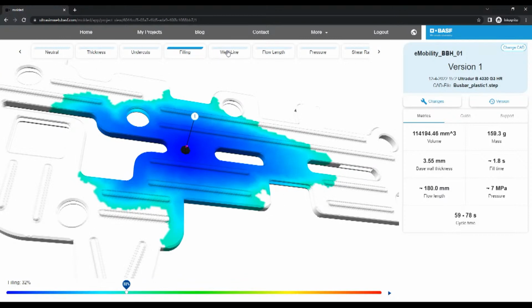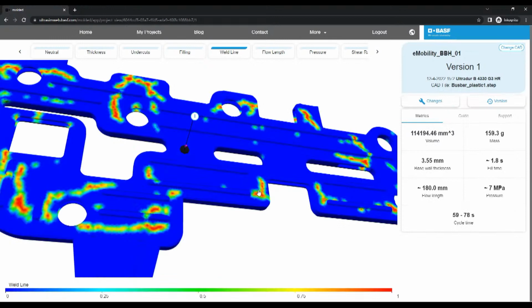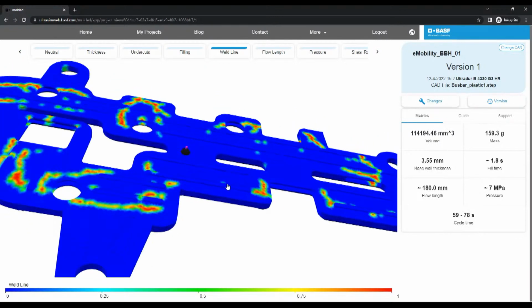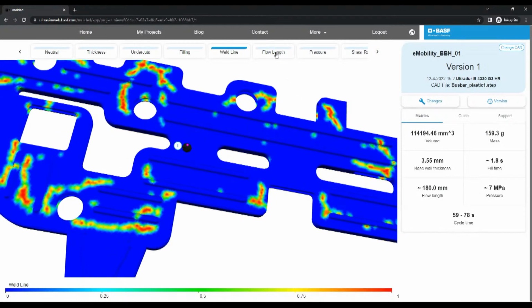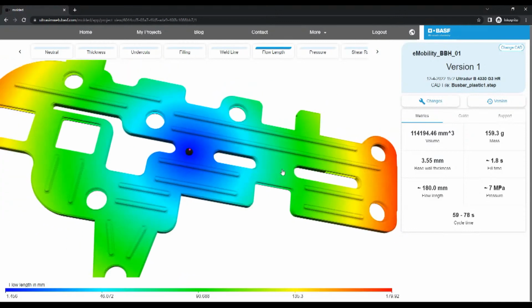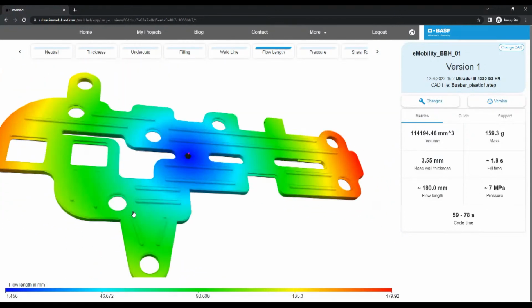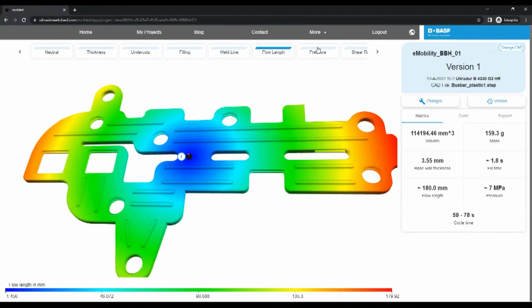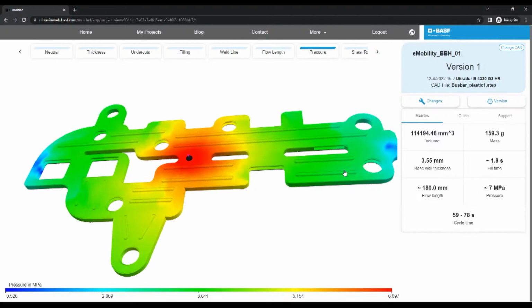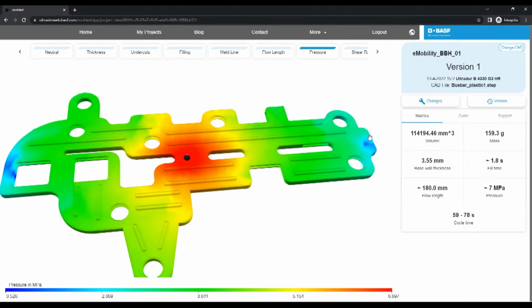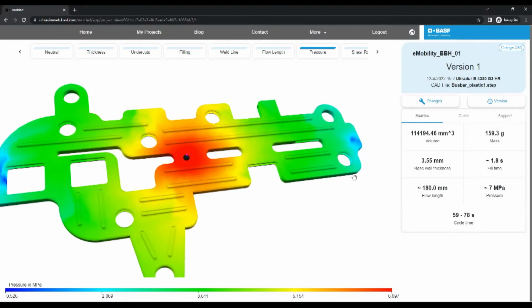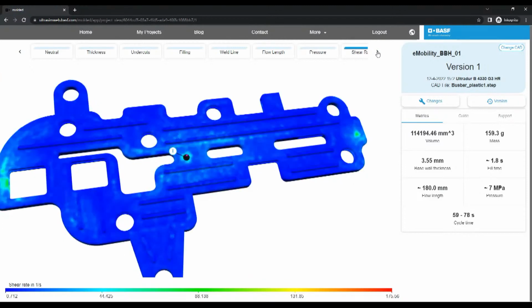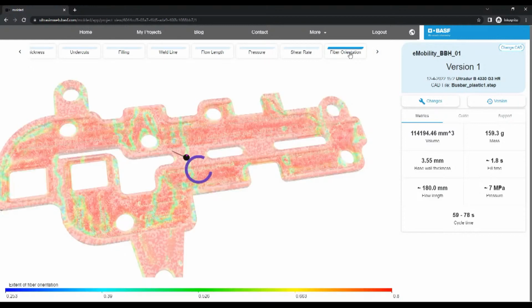I also can check out the weld line indication. Here you can see the weld line forming with different visualization. You can also have a look at the flow length, especially interesting for longer parts. You can also check out the pressure. This is the pressure which is needed to fill the part. Here we see in the edges of the part some low pressure areas. We have also included a shear rate indication, and for glass fiber filled materials we've also added fiber orientation visualization.